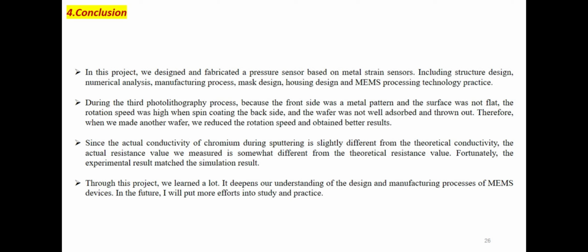During the third photolithography process, the front side had a metal pattern and the surface was not flat, and the rotation speed was too high when spin coating the back side, so the wafer was not well absorbed and was thrown out. So when we made another wafer, we reduced the rotation speed and obtained a better result.